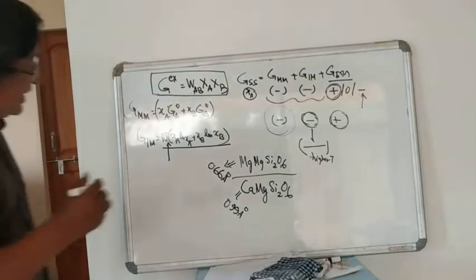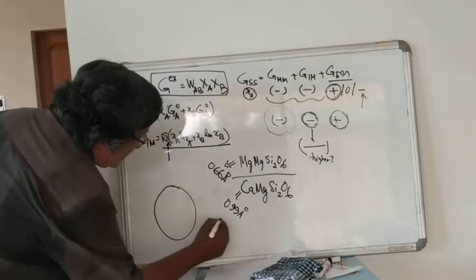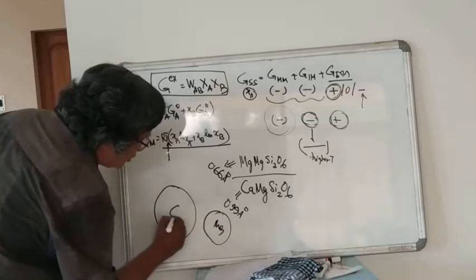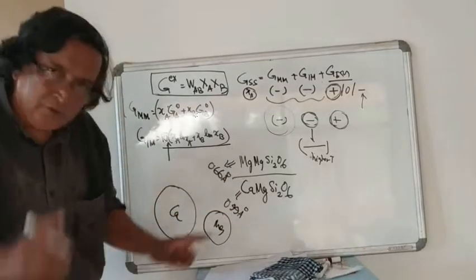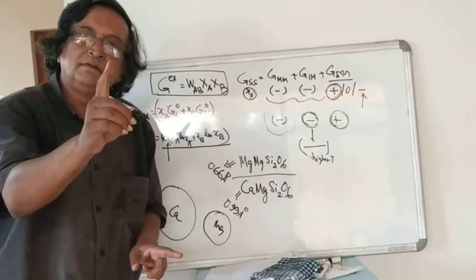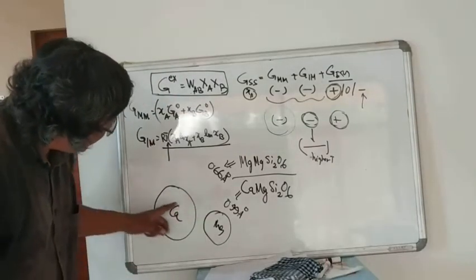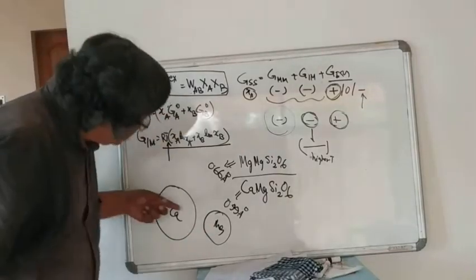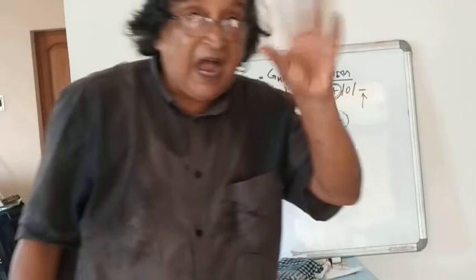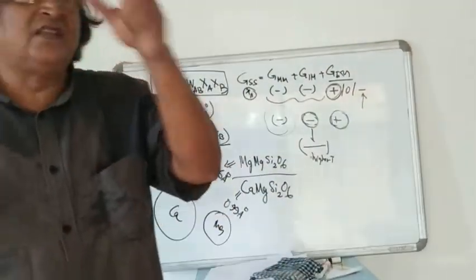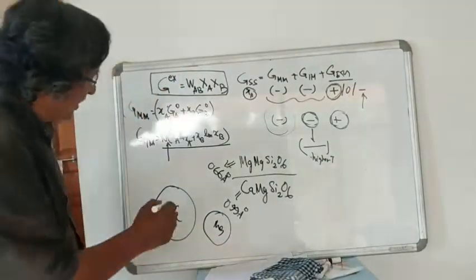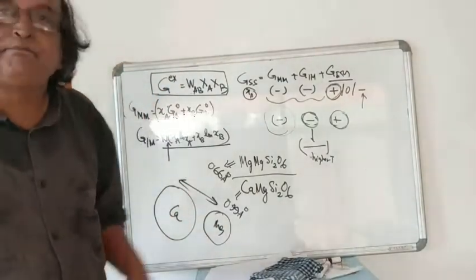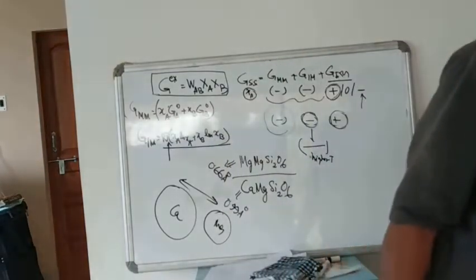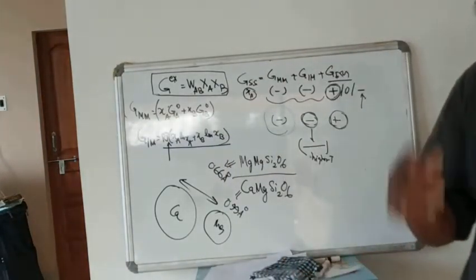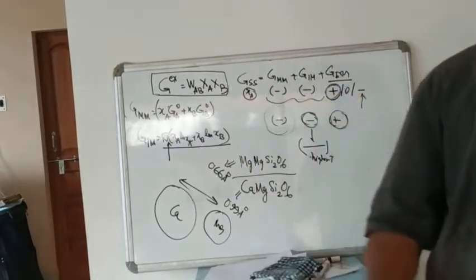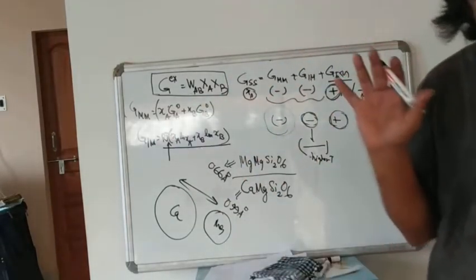So you can imagine that calcium has a much larger ionic size than magnesium. Although both are bivalent, the size difference is very large. So such differences will be associated with high WAB values. Chances are they will exsolve. Actually, they have an immiscibility gap. Now, this is not a course in mineralogy. We could have gone into great detail about the octahedral position, everything, but we can't do that.